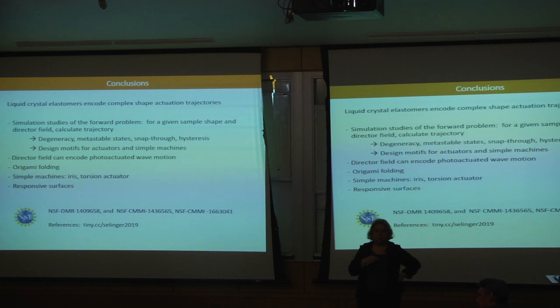Yes? How is the splay geometry made? Okay, here's how it works. The experimenters have different surface treatments which promote liquid crystal alignment in different geometries on the substrate. So when the substrate is rubbed, the liquid crystal wants to lie parallel. And there are some other ways to do it, but that's one way. For the homeotropic anchoring, that's done with a self-assembled monolayer. So you put a chemical entity on the surface that has surface tension such that this is the lowest energy configuration. So that's called homeotropic anchoring.